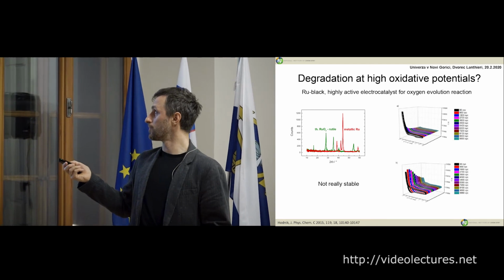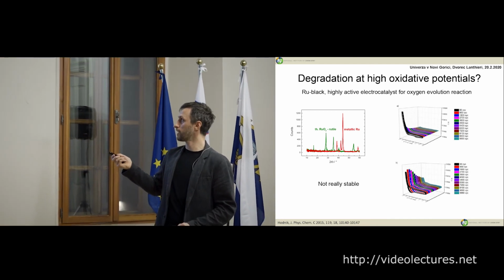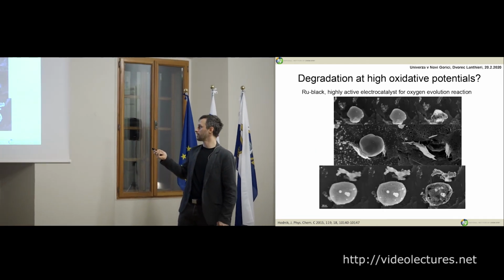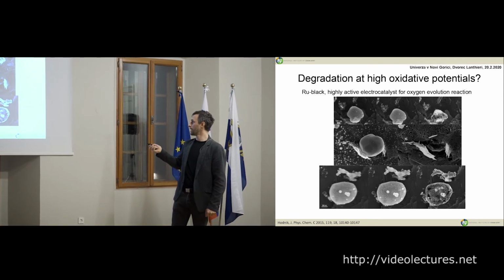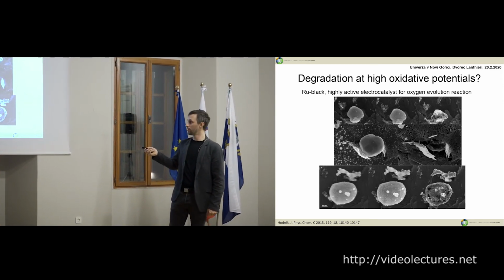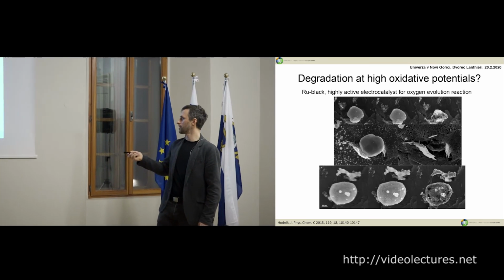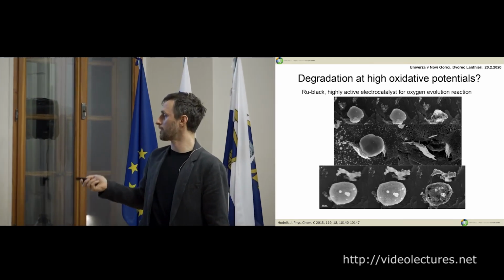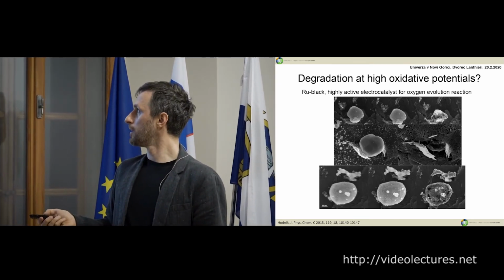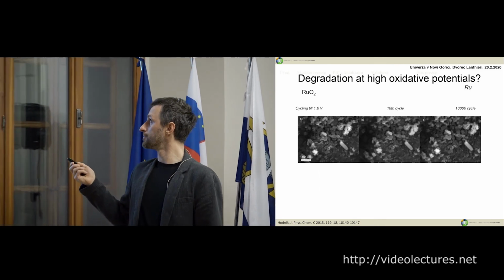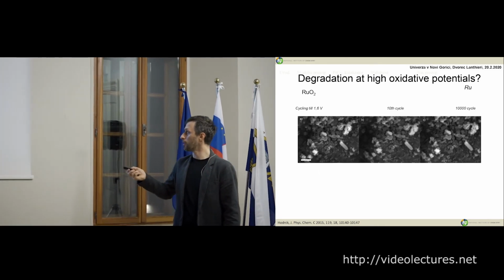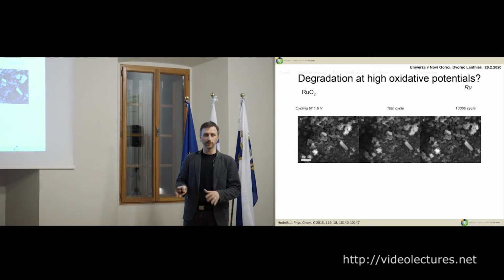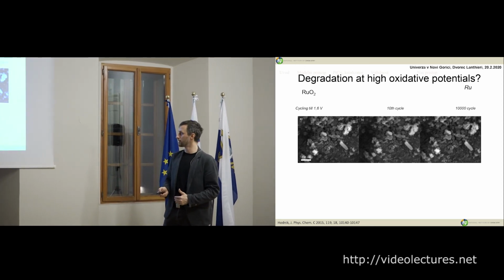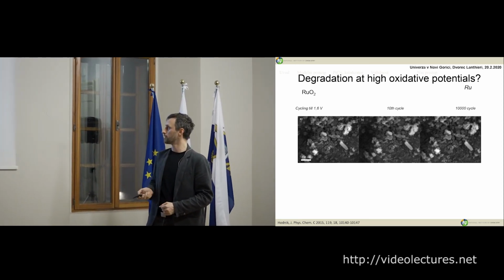So this is before cycling, first cycle, second cycle. Before, and then 10th cycle, you can see everything is dissolved. This is again first cycle, second cycle. And for the ruthenium oxide, there's not much change, but something is happening which is decreasing the activity. So we need to study this further.